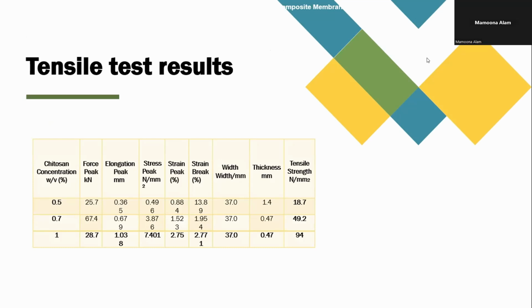One has 0.5 gram, another has 0.7 gram, and the third one has 1 gram of chitosan. The 1 gram of chitosan shows the maximum strength, and you can see the result is 94. While making these membranes, I kept PVC in a constant amount of 1 gram. So I took 1 gram of PVC and 0.5 gram of chitosan in one membrane. That was 1:0.5. The other is 1:0.7, and the third is a 1:1 ratio. The best results strength-wise were found at 1:1. 94 N/mm2 tensile strength was found in that.